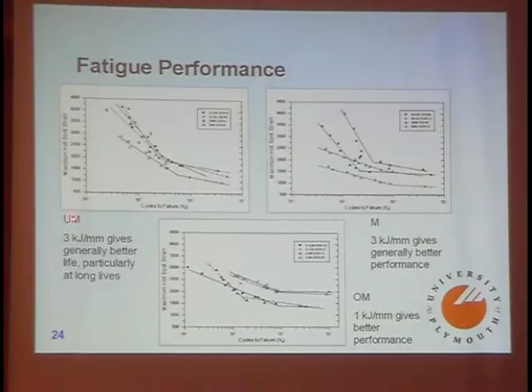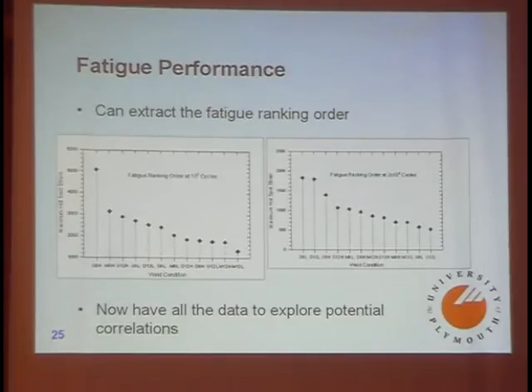And you can say that if you're using undermatched filler metal, 3 kilojoules per millimeter generally gives better life, particularly long lives. Again, high heat input is better there, but interesting with the overmatched, the low heat input gives better performance. So it's hard to draw generalized rules out of this. But this is what I'm interested in. I'm interested in the fatigue ranking at 10 to the 5 cycles and 2 million cycles. So I now have a ranking of the performance of these various welds, and it is different at those two lines.